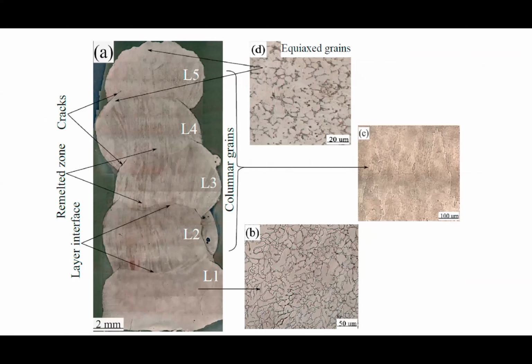And along a long columnar grain with a length of a few millimeters have been formed at the intermediate layer. So usually the intermediate area of the WAAM contains columnar grains that grow throughout the layer. At the same time, in the present sample, the columnar grain grew within one layer, and the precise interface between the layers was formed. So during the deposition of the consequent layer, some part of the previous layers was remelted and recrystallized together with a new layer, and this has led to the formation of a clearly visible remelted zone